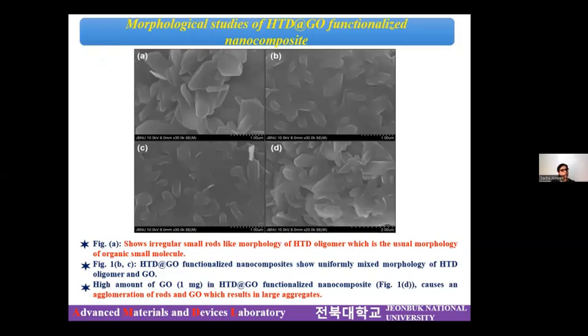From the morphological images, it shows irregular rod-like structures, and this is a very common morphology for an organic molecule. We have found that when the concentration of graphene oxide was a little higher, say for example 1 milligram in the composite, we obtain certain aggregations, and these aggregations are not good for the performance of the chemical sensing. So it is very significant to make the appropriate nanocomposites in their appropriate compositions.